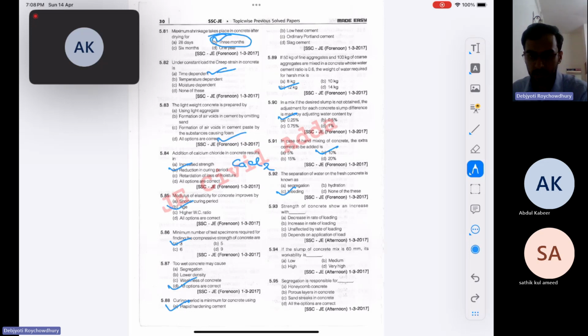The compressive strength of the concrete increases with rate of loading. You can test it with the normal UTM test. You change the rate to a certain value, and you compare the strength you are getting from the lower loading rate. You'll obviously get the higher value for the higher loading rate, because you are giving more jerk to it. So at initial stages it shows this behavior, as the concrete blocks react fast. So actually it is pseudo strength, not the actual strength.